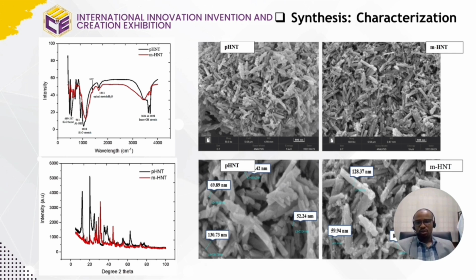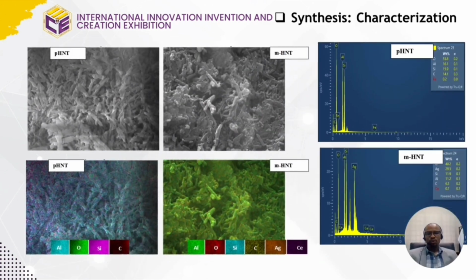And then in the second image also, we noticed that the material has already retained its crystal properties, which is the crystalline properties. And when we investigated the internal structure of the compounds, we noticed that the compound still maintains its cylindrical shape, as you can see from the image, and it has an average size within the nanoscale. So the elemental compositions were also further investigated to see the compositions of these elements, and in particular the modified halloysite nanotube. We notice it contains the cerium nanoparticle as well as silver nanoparticle.